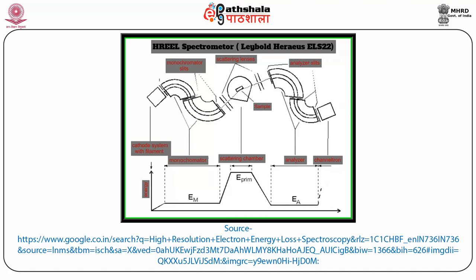The experiment is mounted in an ultra-high vacuum chamber with a base pressure of about 5×10⁻¹¹ mbar. The chamber is equipped with a sample preparation unit, what is called a sputter gun, and provides a LEED system to analyze the surface quality. An evaporator, Omicron EFM3, allows one to evaporate metal films of a thickness from 0.1 monolayer to several hundred nanometers, a really thin layer that can be analyzed with this.